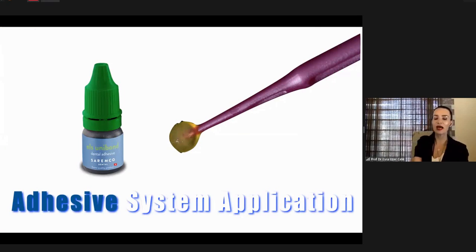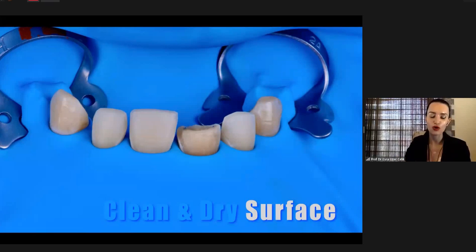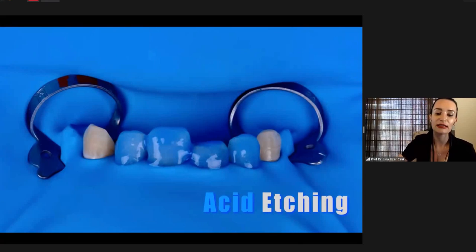And the adhesive system application. In the first part, you select the adhesive system that you will use, but its application technique is also very important. It's a critical issue for longer retention, better marginal adaptation, and also preventing marginal discoloration. As you see, first, the surface should be clean and dry, because any fluid, any saliva, and also any plaque can buffer the acids of your adhesive systems. After that, unfortunately, you can't make enough demineralization.